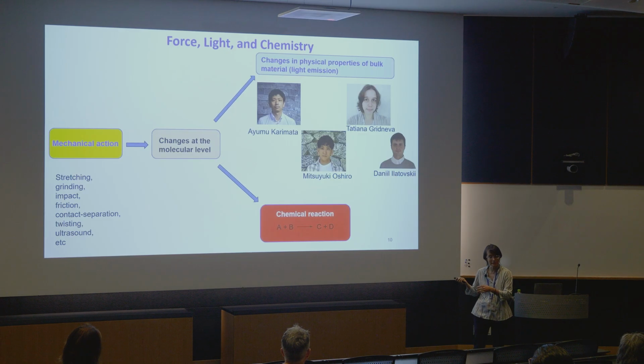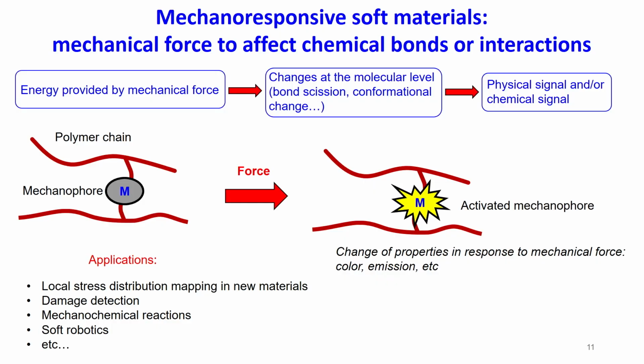So we were mostly interested not in hard materials like crystals of sugar, but in soft materials. So we wanted to make soft materials or polymers where we would use the energy provided by mechanical force to activate certain bonds, to cause changes at the molecular level, and that would result in a certain signal that we can detect. And in polymers specifically, that is often done through this approach. You need a small molecule which contains some weak chemical bonds. Then you incorporate it into the polymer chain, and then, for example, you can stretch the polymer, that breaks the chemical bonds, activates the mechanophore, and causes changes in the properties like transient emission of light or changes in the color.